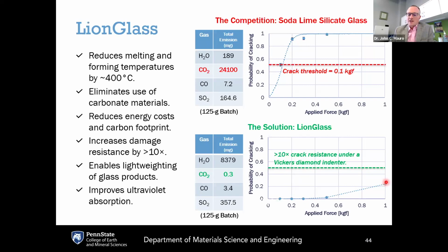And in fact, if you go 10 times that high, which actually maxed out our equipment here, to 1 kilogram force, it's still just a 25% probability of cracking. So the damage resistance is at least 10 times higher for LionGlass.